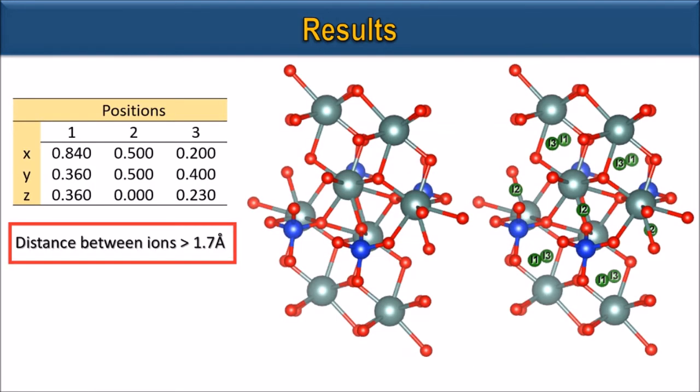The interstitial defect positions considered for both structures are shown in this table. The interstitial positions were chosen considering the empty volumes in the unit cell for both structures and taking into account a minimum distance of 1.7 angstrom from the interstitial site to the first neighborhood species.